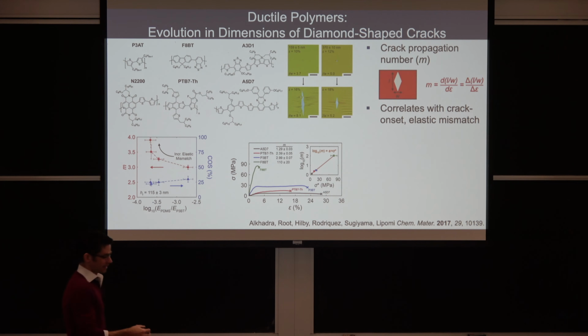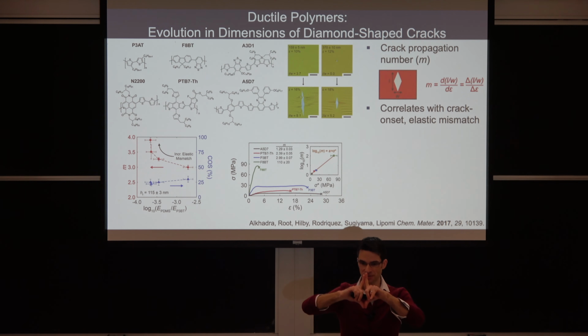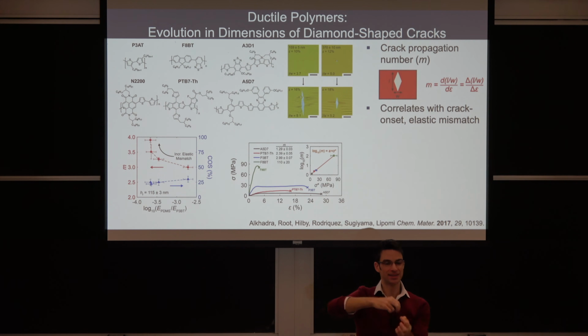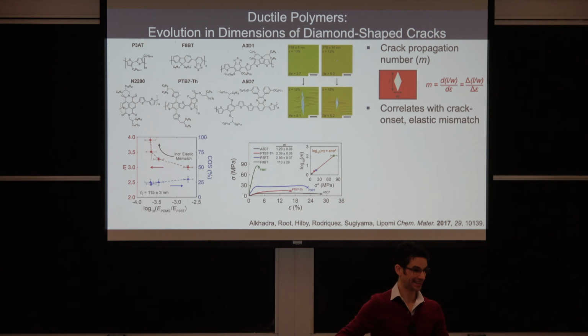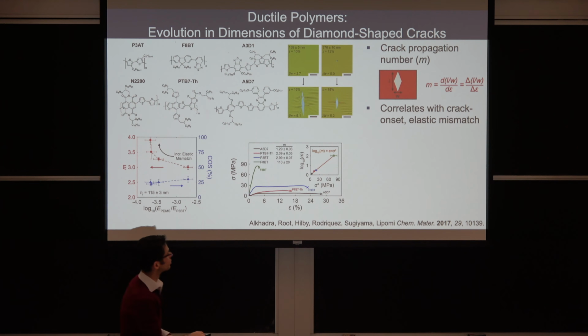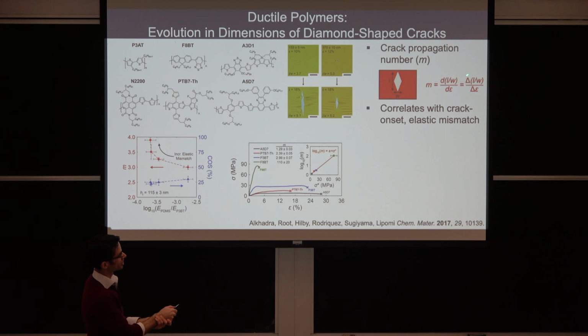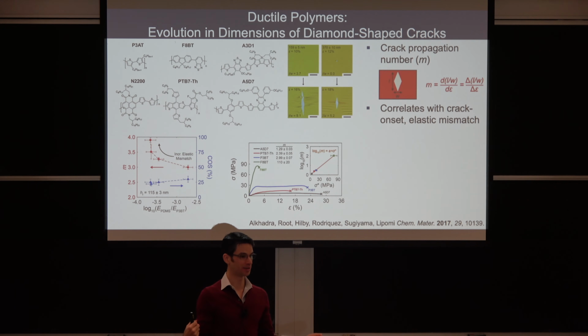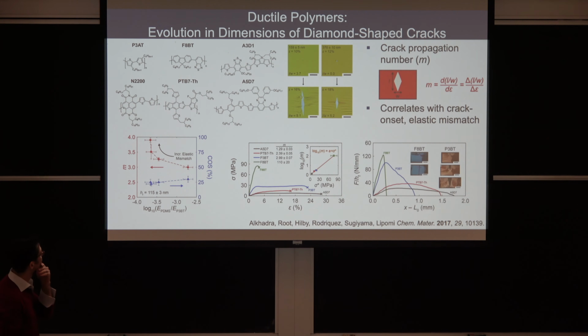So for example, these diamond-shaped cracks for ductile films, as you elongate them, the more brittle they are, the longer they get compared to how wide they get. And if you plot the growth rate of the aspect ratio as a function of strain, and you take the log of that, you get a straight line when you plot it against the fracture stress, which is pretty cool because we didn't even need to do a pull test on the material. We just needed a microscope and to stretch the material. And we did it for a range of different organic semiconducting polymers here.